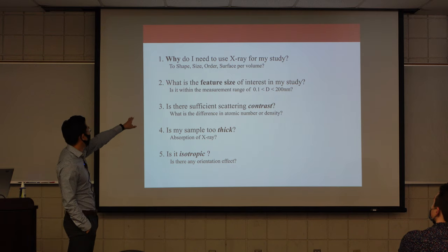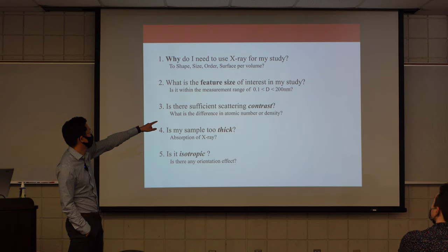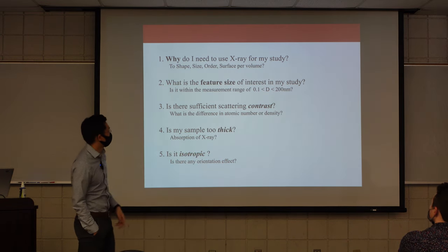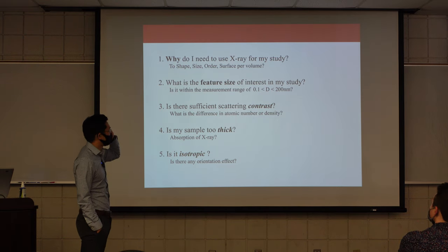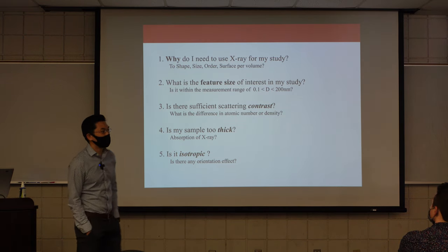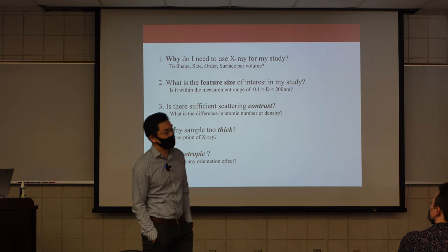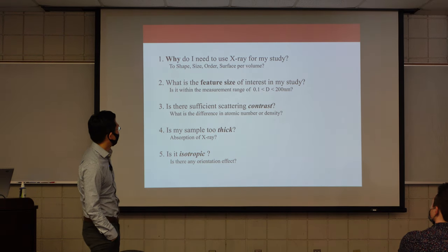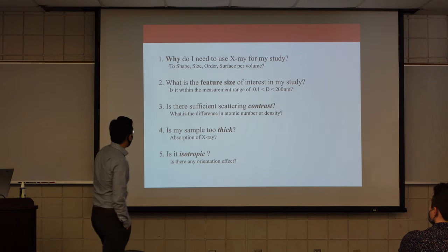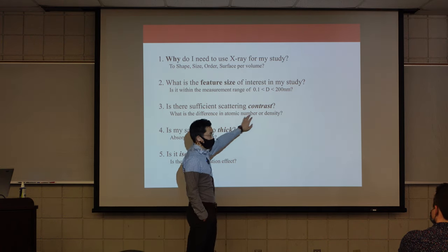For block copolymers, we need to think about whether the feature size of interest is within your study. Is the measurement within the range of this particular size, which is accessible with the instrument here using this X-ray? Block copolymer has a periodicity on the order of tens of nanometers, up to maybe 100 in some extreme cases. Or bottlebrushes at 100 or 200 nanometers, so certainly feasible. This one is a little bit tricky. Is there sufficient scattering contrast? Okay, this is a little bit